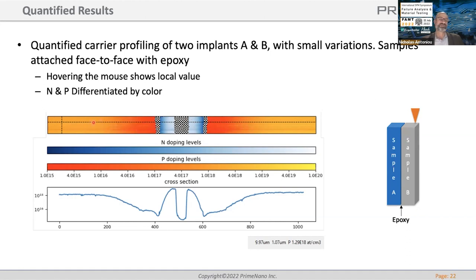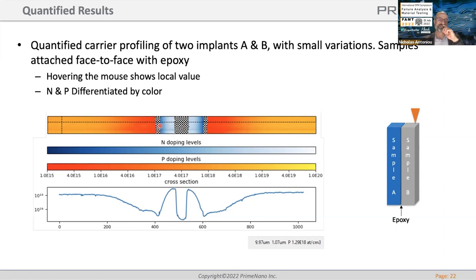You can place your cursor at any position and get a line cross-section that looks very similar to a SIMS depth profile but with nanoscale resolution in depth. The point of this exercise was that lot A and lot B had a slight difference in their peak concentration — a nice way to display that. The checkerboard pattern indicates we were not able to resolve a polarity or dopant in that area. For the epoxy that's obvious, but we're also seeing the depletion region between the n and p where there are no carriers — identifying the space charge region.